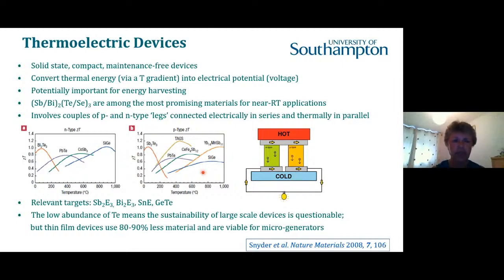The diagrams here indicate the sorts of materials that come into this category and just capture a few of the families. I'm not going to spend too much time on this, but just to indicate here, in the N-type material we've got bismuth telluride, and at the same sort of temperature range in the P-type material, we've got antimony telluride. So that's for the room temperature application, combining these two materials is particularly interesting. You can see that going to higher temperatures, a wider range of materials are also of interest, but I want today to focus on the bismuth antimony family.